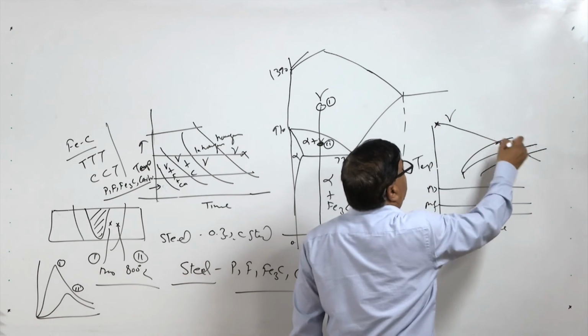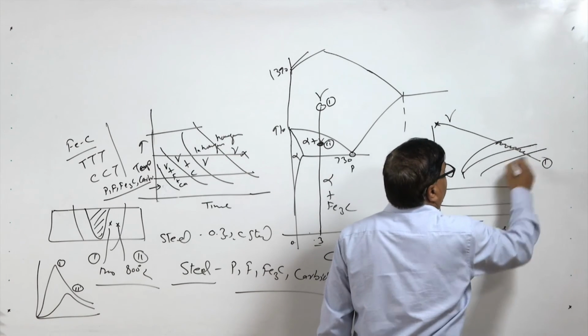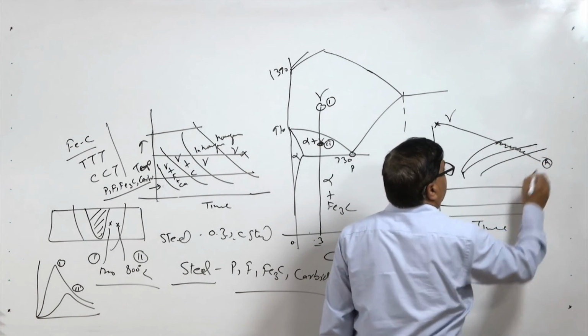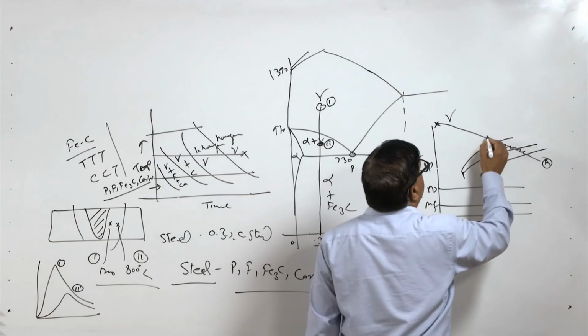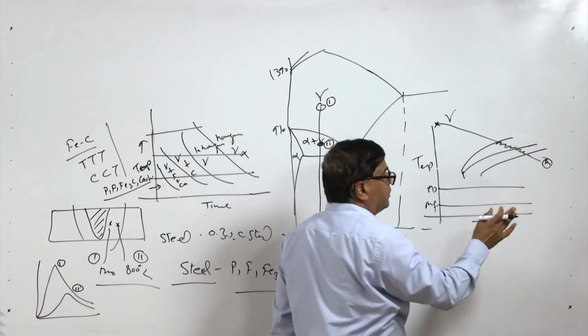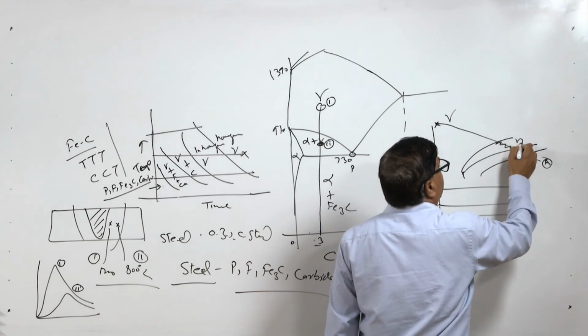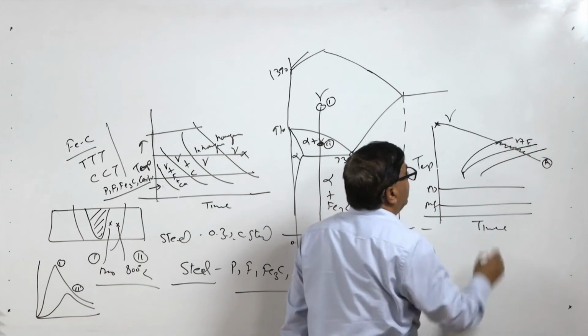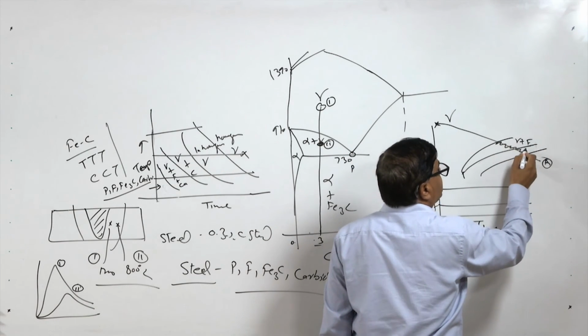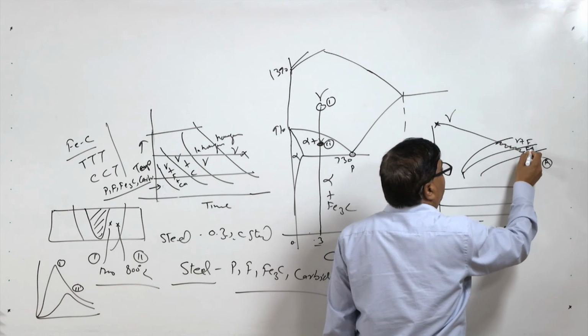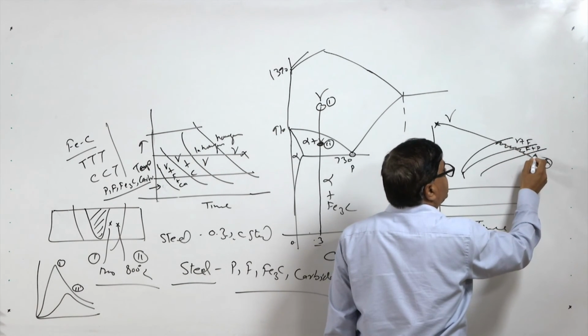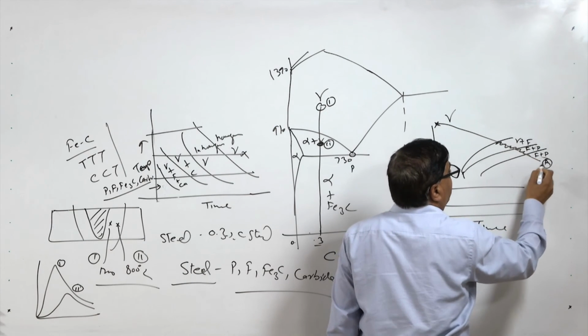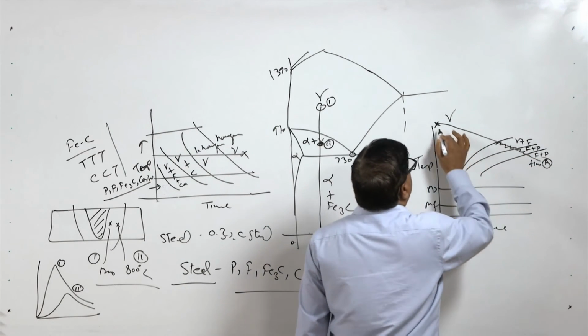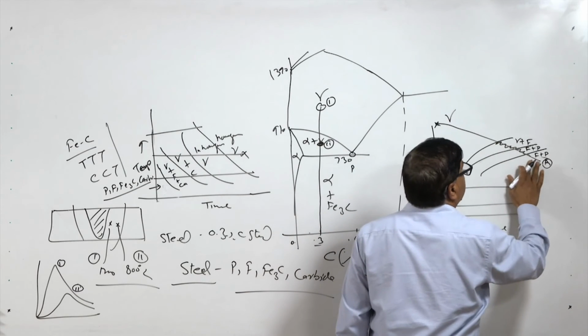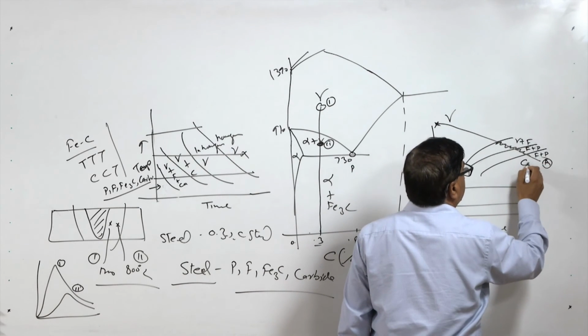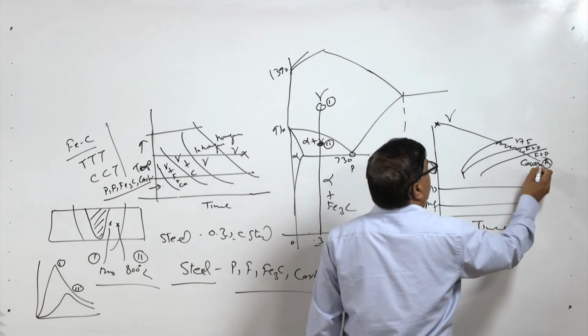Here, as per the cooling rate, say cooling rate 1 or cooling rate A. Cooling rate A is slow. So, here austenite first transforms into proeutectoid ferrite. Here we will have austenite plus ferrite, and then the remaining austenite will transform into pearlite, ferrite plus pearlite. So, here basically we will have ferrite plus pearlite, which is very coarse, because the cooling rate is very slow.